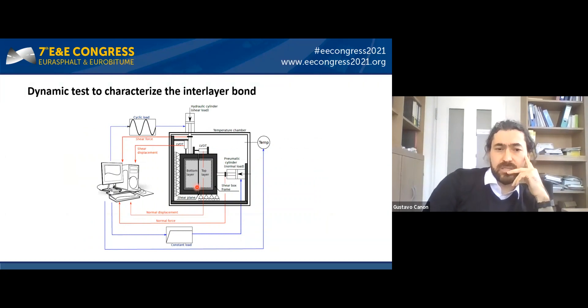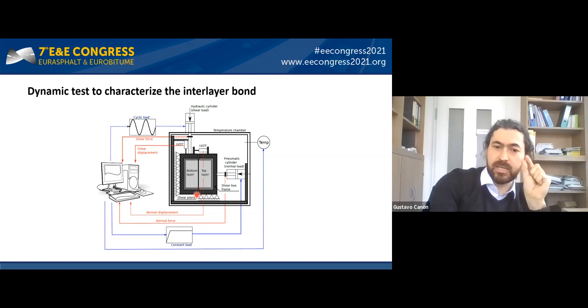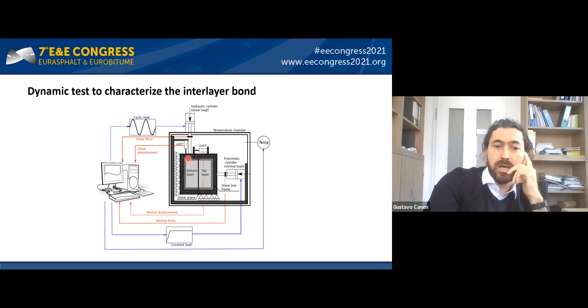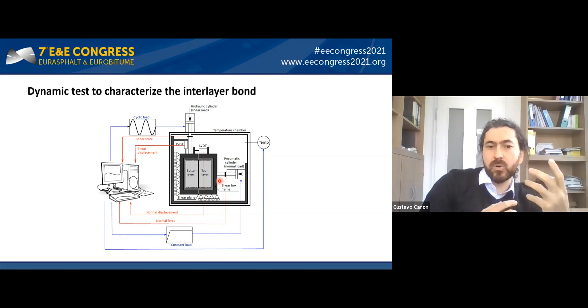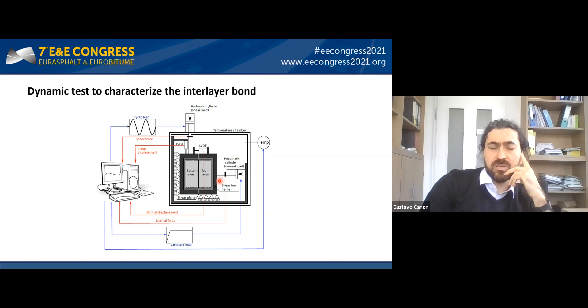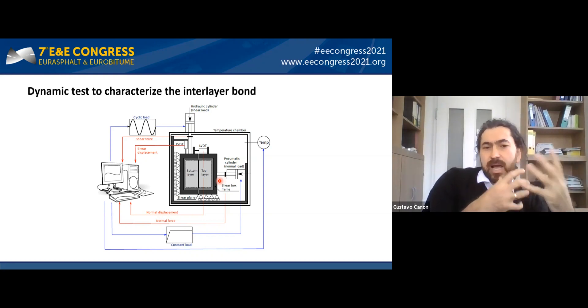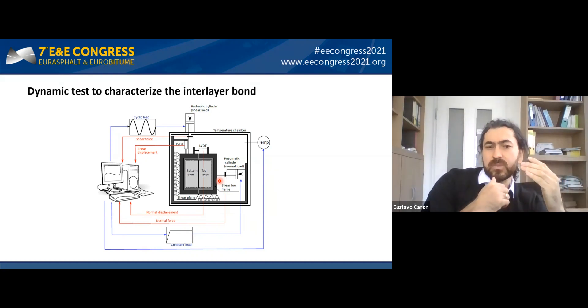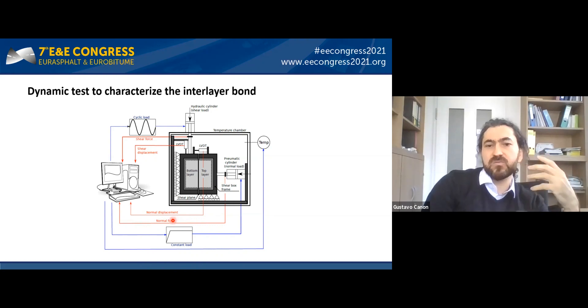In the schematic: on one side we have the bottom layer and on the other side the top layer, with the interlayer area and a one-millimeter shear plane. We apply a cyclic load with the vertical piston, and it is also feasible to apply a normal load — quite important for determining interlayer shear stiffness. This is because the interlayer bond is characterized by two mechanisms: friction between the two asphalt layers and the adhesive effect of the tack coat. The friction mechanism is highly dependent on normal pressure, so by applying this normal load we can determine the friction coefficient between the asphalt layers.